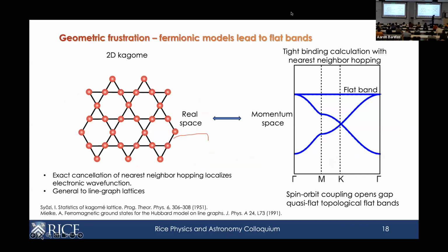So this geometric frustration, recently people have realized, can also be a mechanism to produce electronic flat bands. Let me just illustrate that really quickly here. So here's our lattice. It turns out that there's an exact cancellation of the nearest neighbor hopping, such that there is no hopping out of these hexagons, such that the electronic wave function is localized within each of these sites.